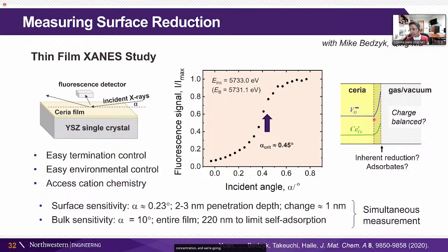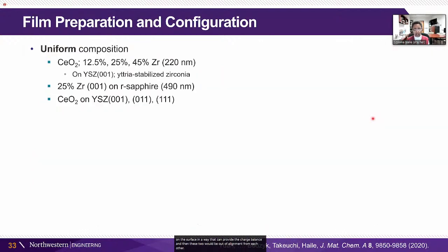And we're going to make the assumption that the two are charge balancing each other, and there's nothing else on the surface. This is a high enough temperature, most of our measurements, that there's nothing at the surface which is providing some charge balance. At a lower temperature, you might expect some hydroxyl groups or something like that to be on the surface in a way that can provide the charge balance, and then these two would be out of alignment from each other.